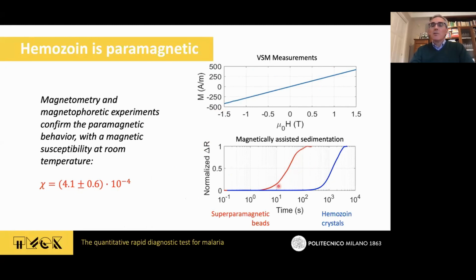And in this experiment, we also tried to compare the magnetically assisted sedimentation of the hemozoin crystals. Here you see the normalized resistance variation as a function of time during magnetically assisted sedimentation on the electrode. And you see that the blue curve is strongly delayed with respect to the red curve, which corresponds to superparamagnetic beads. As here the magnetic susceptibility is around 1, it's clear that here the susceptibility must be much lower than 1, and it's compatible with this 4 × 10⁻⁴. So they are not superparamagnetic, but even so, the magnetism is strong enough to allow for the separation.